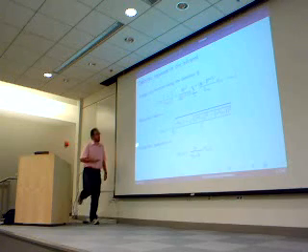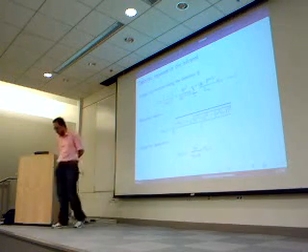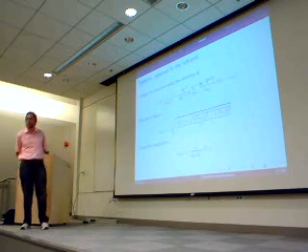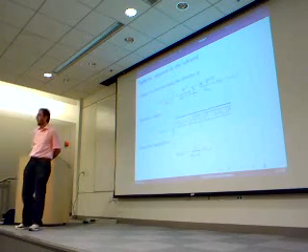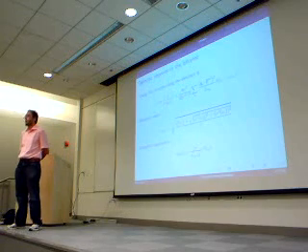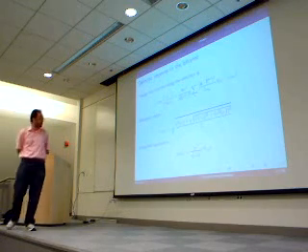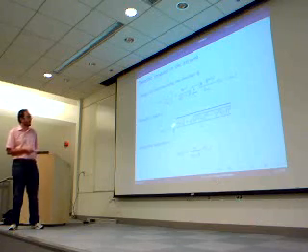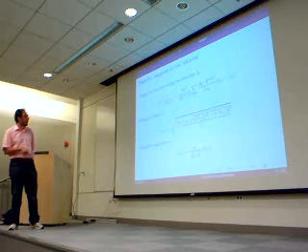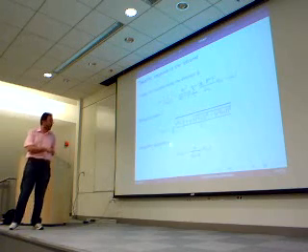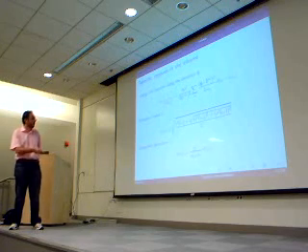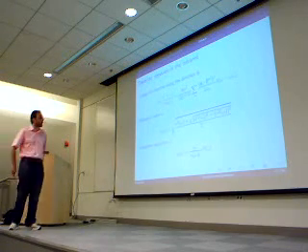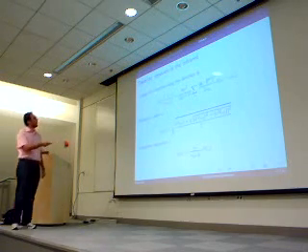So now, just to give some other formulations, in most experiments, for example in FTIR, what is reported is the absorption spectrum. Once you calculate the imaginary part of the response that we've done before, you can calculate the absorption spectrum just with this formula here, in which c is the speed of light.